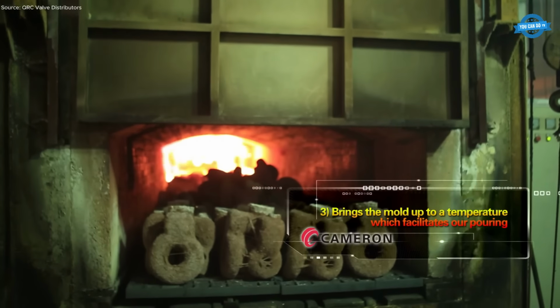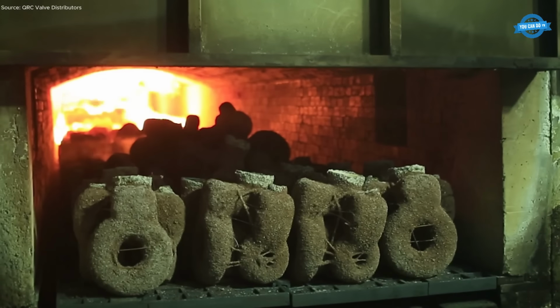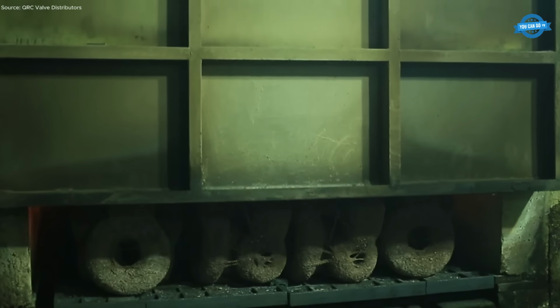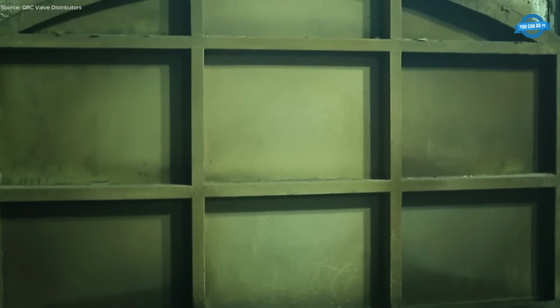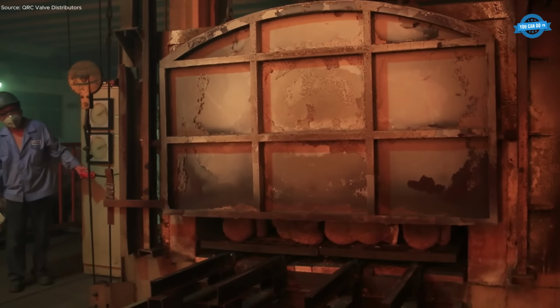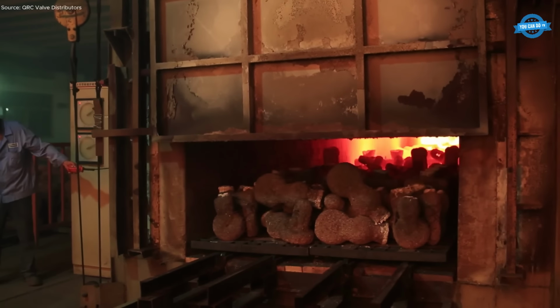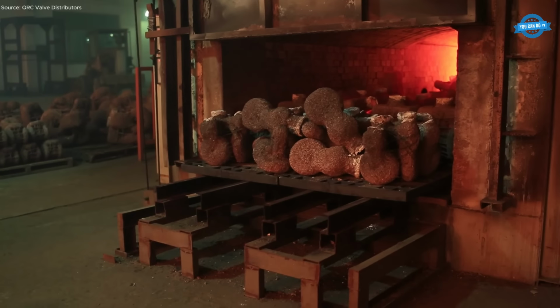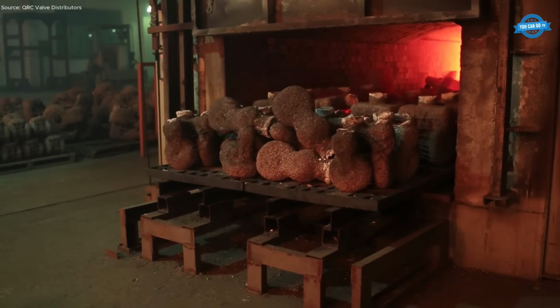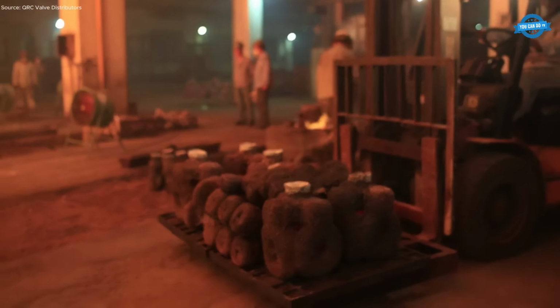The ceramic shells are fired in furnaces at up to 800 degrees Celsius, which strengthens the mold, eliminates residual wax, and ensures the mold is preheated to promote proper metal flow. In parallel, molten steel is prepared in induction furnaces. The chemical composition of the melt is controlled by spectrometer analysis. Once verified, molten steel is poured into the preheated shells under carefully regulated conditions to minimize shrinkage and voids.